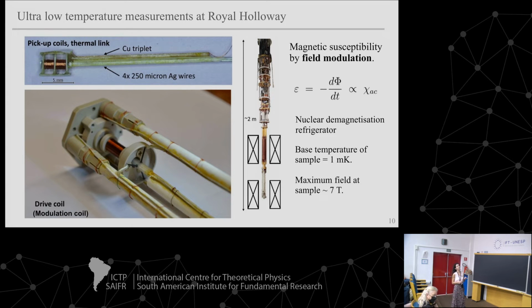This is just from Faraday's law, or the flux law. So the EMF induced across the pickup coils is proportional to the rate of change of magnetic flux, which we provide with the modulation field. So that's the field modulation technique. And that's proportional to the magnetic susceptibility, which we can then detect. All of this is sitting down here inside the sample magnet, which can go up to 9 tesla, but we didn't measure above 7 tesla during these measurements. Mostly we stayed between 2 tesla and 6 tesla.